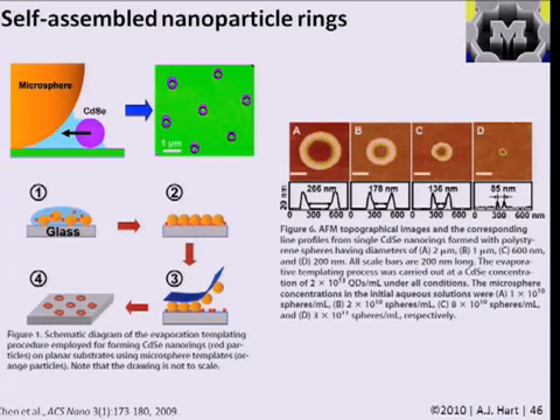simultaneously. First, the microparticles pack into monolayers as we expected, and second, after the liquid kind of recedes beneath the space between conjoining microparticles, the meniscus does another thing. It takes the nanoparticles down into the crevice under each microparticle and evaporates them to form a ring. And so here on the right side, we see AFM images of the rings that are formed by executing this process with polystyrene spheres of different diameters. And you can see that the height and the width of these rings, or the diameter of these rings, generally scales with the diameter of the sphere that is used to create the template.